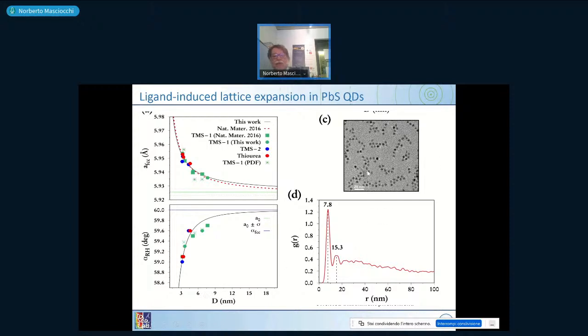So this is a picture of our tiny lead sulfide deposit on the surface, on a carbon surface for TEM measurement. And again, you see that they don't just arrange in a random manner, but they try to give sequences. By counting the position of this material, counting the distances, you can easily make a so-called radial distribution function.